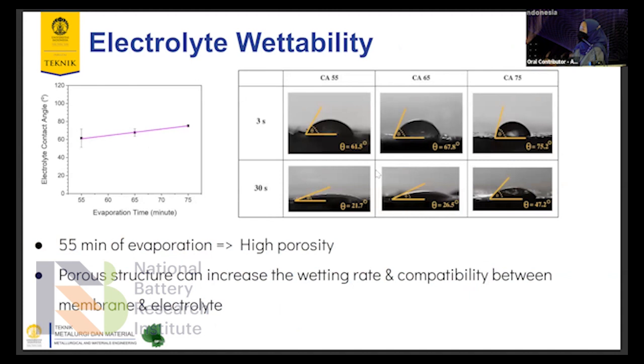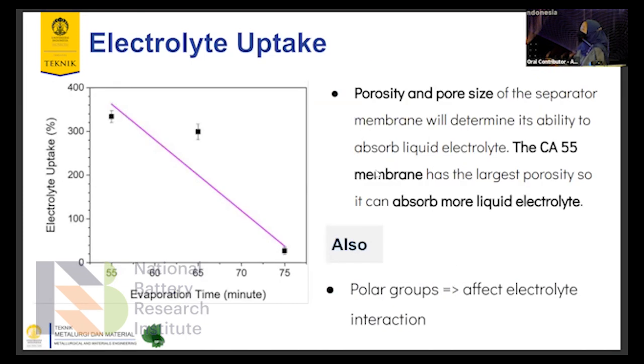And then the electrolyte wettability. This is also related to the porosity. The 55 minutes of evaporation has the highest porosity because the porous structure can increase the wetting rate and compatibility between membrane and electrolyte. We also observe after dropping the electrolyte at 3 seconds and 30 seconds. We know that the wetting rate is quite high because there is a change in the contact angle. And then the electrolyte uptake, it is also related to the porosity. The 55-minute evaporation time shows the highest electrolyte uptake. This is also because of the polar groups that affect the electrolyte interaction, and there is also an interaction with electrolyte through Coulombic interaction.